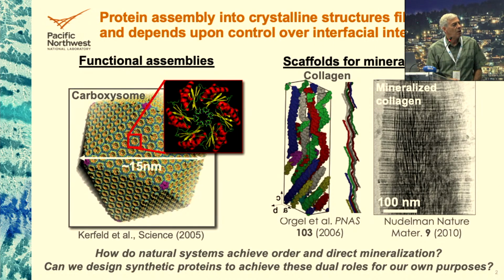Individual collagen monomers, so-called tropocollagen molecules, three of them assemble to make this trimeric unit, and those trimers then assemble into a pseudohexagonal fiber where the end of one collagen molecule comes some space before the start of another, and so it creates regions that are called overlap and gap zones. And mineral precursors can diffuse in; these then assemble into these quasi-hexagonal packed structures. So if we looked at a cross-section, you'd see a hexagonal array.